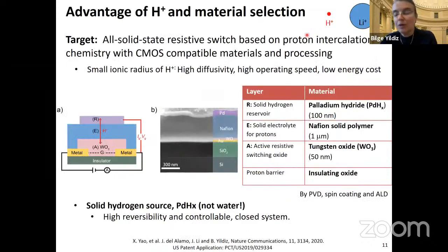So why proton? This is the smallest cation that we can work with in solid state. It has nearly zero, if not negative, ionic radius compared to the 0.9 angstrom radius of lithium. So you are dealing with the smallest ion that you can work with, and that gives you the advantage of lower energy needed to move the proton in solid state. And that should then translate to lower energy consumption in the device and also faster operating speed with the lower energy. That's why we wanted proton.